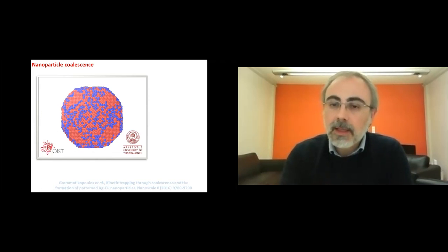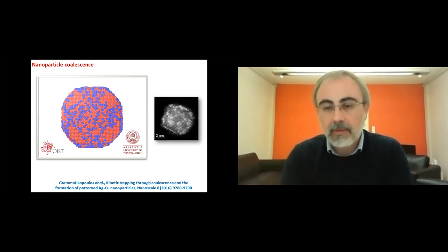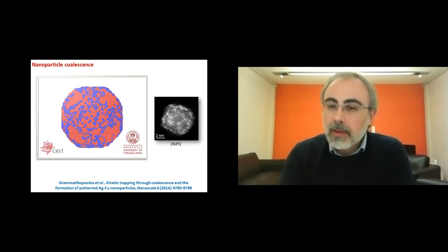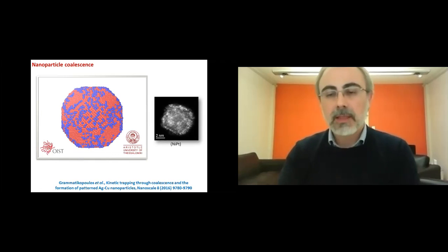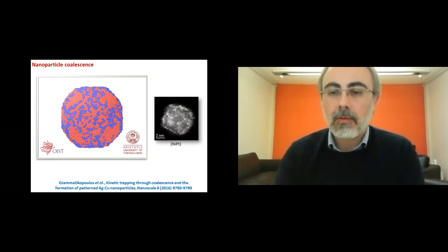But since then, we actually observed exactly, or very, very similar case for nickel platinum nanoparticles, where you can see here the platinum atoms are the bright spots, and as you can see, they are decorating specifically the edges of this roughly truncated octahedral nickel core, avoiding the facets. This is something we haven't published yet.